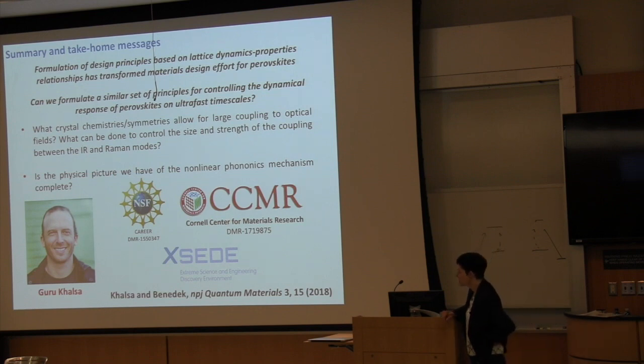All of these experiments are done at very low temperatures. We have to, because here the Néel temperature is 30 Kelvin, so you'd want to be below that and as low as possible. In the experiments that I've seen, the temperature change is controlled to within about 2 Kelvin.